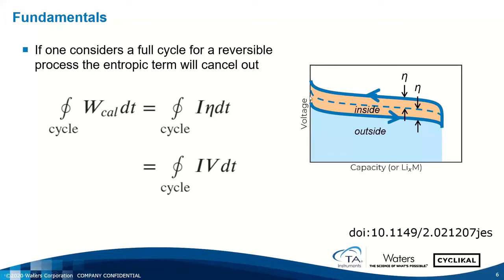And then the nice thing with the overpotential term is that if we go over a cycle, on discharge here, it would be the area under the dashed line, and on charge, it would be the area above the dashed line. But over a cycle, we don't need to know what the value of the dashed line is. We can simply look at the potential that we measured, the voltage that we measured. And so over a full cycle, the integration of the heat measured in the calorimeter will be equal to the area here inside our voltage curve, right? So this area has units of energy. And so over a full cycle, we can now relate the heat of the calorimeter to values that we measure directly at the cycler, namely the current and the voltage of the cell.